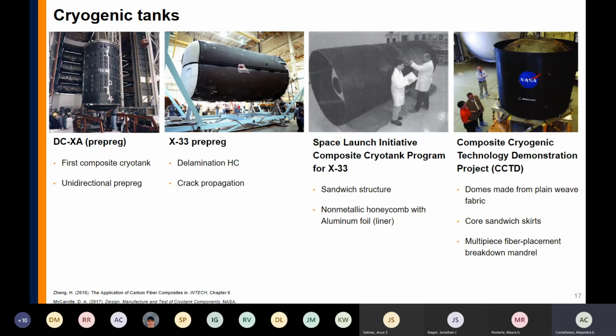But again, these two projects were canceled. They didn't mention why. It wasn't because of composites, but they just canceled the project and never disclosed why they did that. But then they had the CCTD, or the Composite Cryogenic Technology Demonstration Project. They actually were able to manufacture one of those cryogenic propellant tanks made of composite. But instead of using unidirectional, where all the layers are pointing in one direction, they used plain weave or woven fabric. This will prevent the leak or the cracks from propagating faster than in a unidirectional composite.